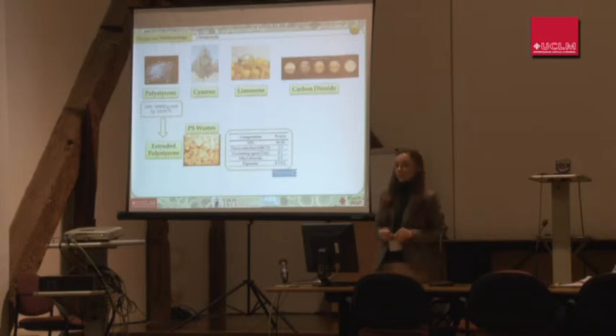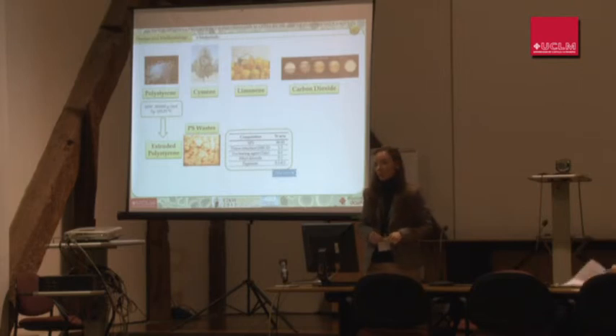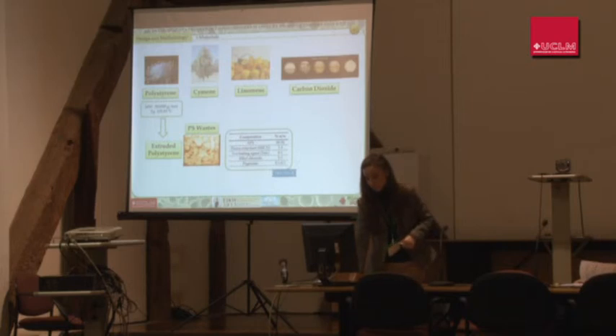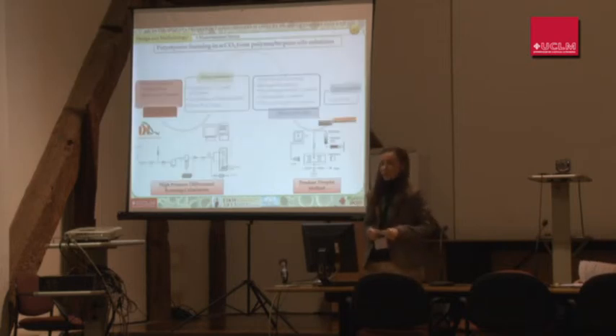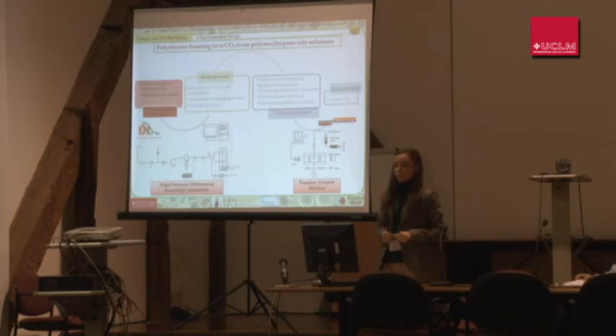The raw materials that were used were polystyrene, and also real wastes that come from Tecnalia, two natural solvents, cymene and limonene, and carbon dioxide as anti-solvent and foaming agent. Initially, we selected the working conditions according to the glass transition temperature of the mixture that we measured in a high-pressure differential scanning calorimeter, and the interfacial tension that we measured by means of the pendant droplet method in a high-pressure view cell that was developed in Eurotechnica, Germany.